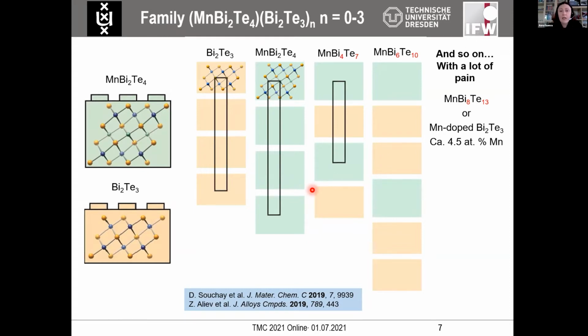And in this system, you can also get access to further representatives of the family. So natural heterostructures where septuple layers periodically alternate with the quintuple layers of bismuth telluride. It gets progressively difficult to obtain these compounds because the melting points of these further analogs get closer and closer to the melting point of bismuth telluride.